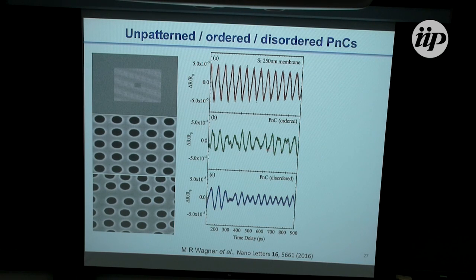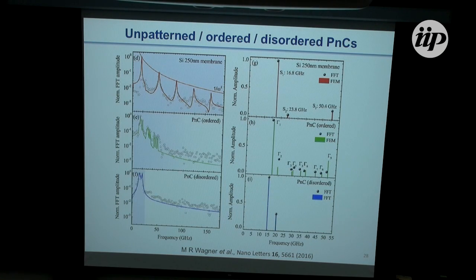These oscillations vary with respect to the reference membrane, the ordered membrane, and the disordered one. All these are on the scale of 1 nanosecond. And if we take this further, taking the Fourier transform of that, you see a family of peaks that become, A, fewer, and B, all shifted to lower frequencies. So that's the influence of disorder on the lifetime.